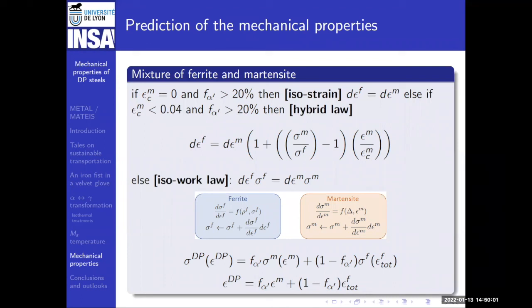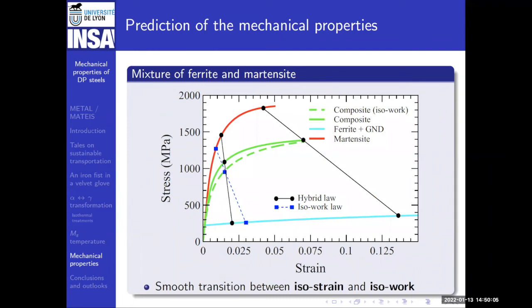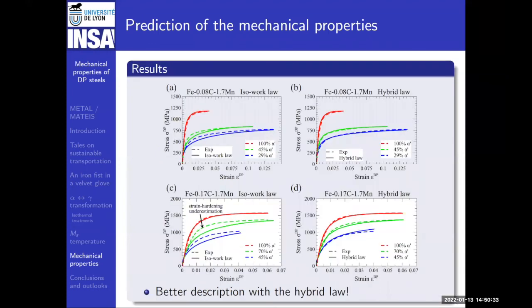So we end up with a constitutive law for both phases. Here is a graphical view. At the beginning, you mix with a vertical line, isostrain, the hard martensite and the soft ferrite. At the end, this is isowork, so this is this mixture law. And during the hybrid domain, it transforms from a vertical constitutive law to this law. And this is how, from this curve and this curve, we build this curve for the martensite. And this is the validation of the model for different steels, depending on the carbon composition, the manganese composition, and we checked that the hybrid constitutive law leads to a better description than what was usually done using an isowork law from beginning to end.